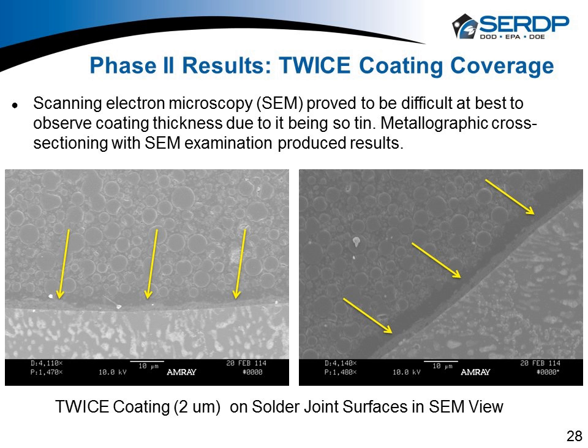So when we spray thinking we're getting 2, and we do out on a flat unencumbered surface, when you get to the topography of a circuit board on curved surfaces and things that have Z height, we're getting from 1 micrometer to 1.5 micrometers. So we don't quite hit this 2, but we clearly stay above 1.